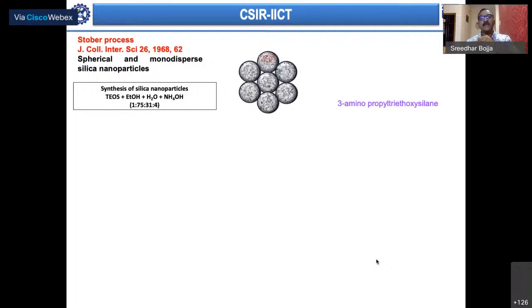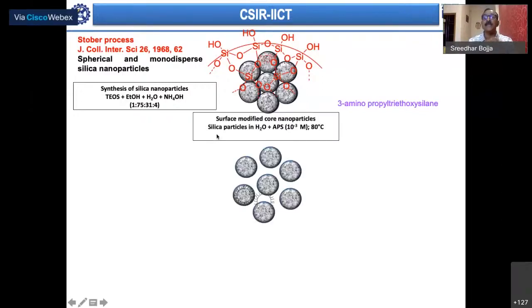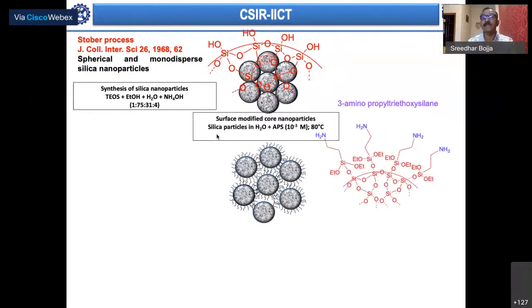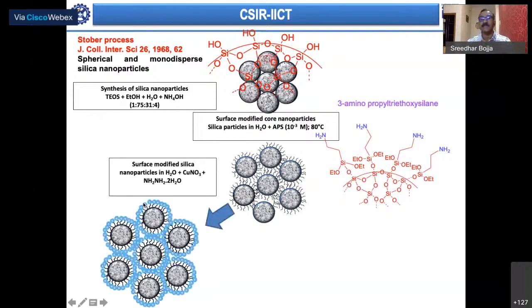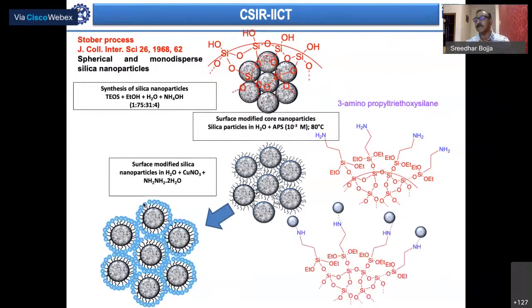So what we try to do is functionalize it through modification. With silica nanoparticles, the OH terminals normally present do not allow metal nanoparticles to sit on them. To build a surface friendly relationship, people use surface modifying agents like 3-aminopropyl triethoxysilane. When you use this modifier, the OH group terminals become NH2 terminals. Then you can have metal ions attach on it, reduce them, and have metal nanoparticles on the shell material over the silica core. That is how we synthesized these materials.